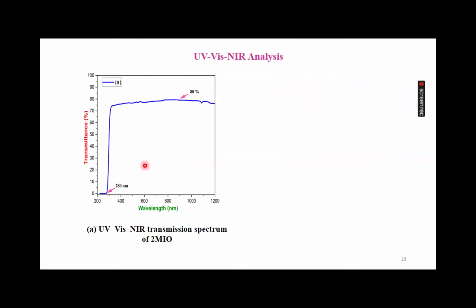UV visible NIR analysis. The optical transmittance was investigated for the 2MIO crystal using UV visible NIR spectral analysis, which would confer factors such as the region of optical transmittance and the lower cutoff wavelength. Generally, efficient nonlinear optical materials possess a cutoff wavelength less than 300 nanometer, such that a wide region of optical transparency is also required. The analysis of optical transmittance of the 2MIO crystal of 1.5 millimeter thickness was undertaken, making use of the recorded UV visible NIR transmittance spectra as shown in this figure.